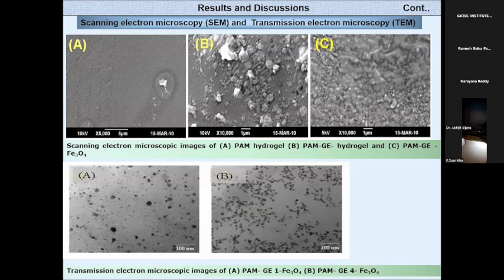In addition to that, we have studied transmission electron microscopy to check the exact particle size. Since we are getting good results on the gelatin-based hydrogels, we have studied G1 and G4. As for the particle size, our particles are coming out at less than 30 nanometers.